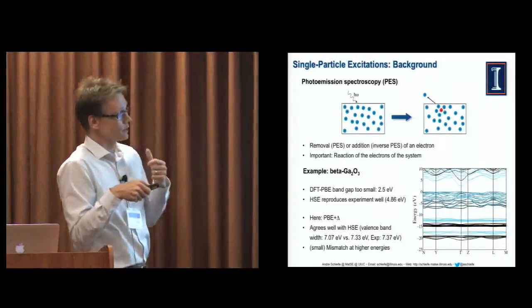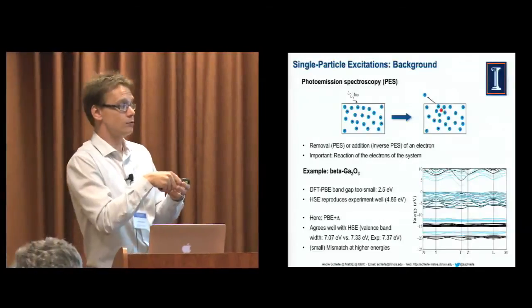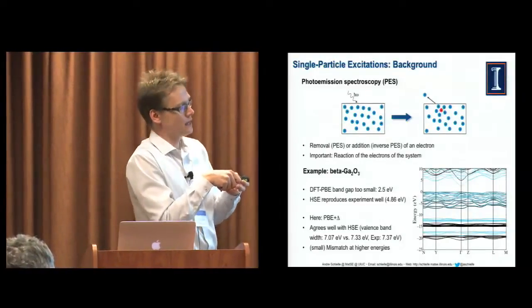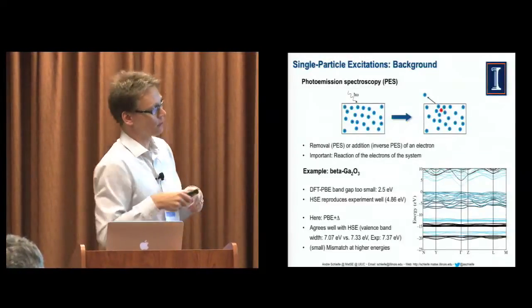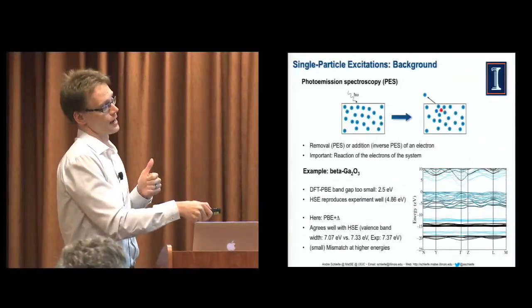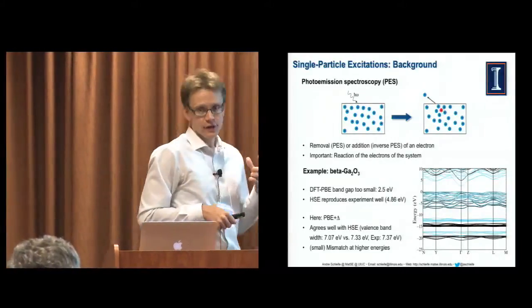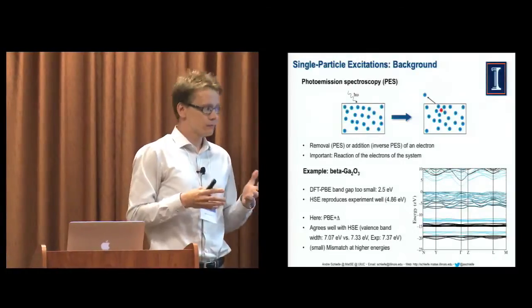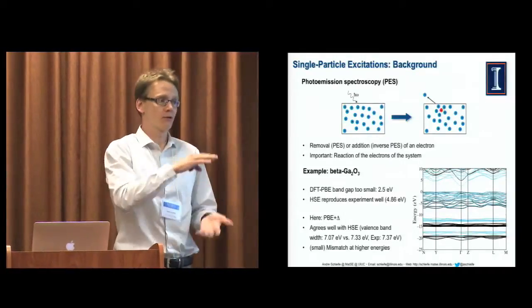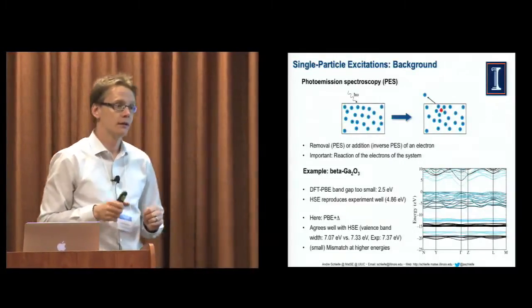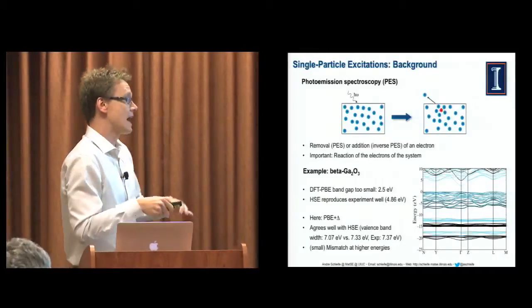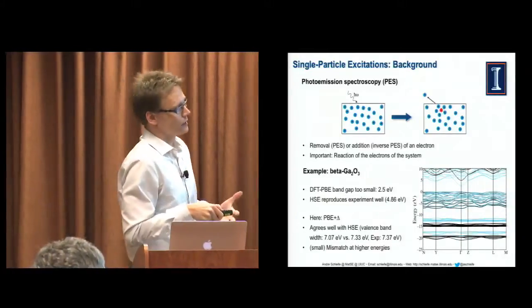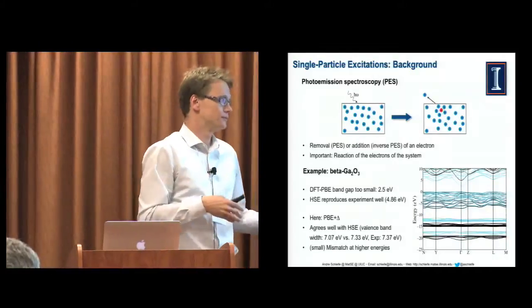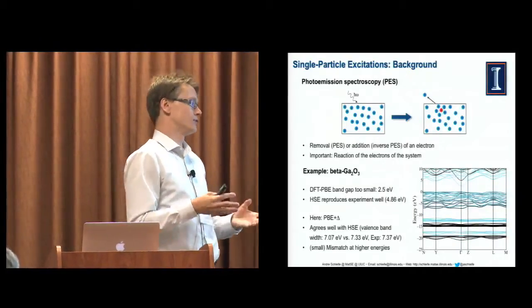If you compare that to experiment, you'll see that this band gap is way too small, right? So in this particular case, we obtained, I guess, 2.5 electron volt. The experimental one is closer to 4.9. That is a tremendous difference, because if you think of optical absorption, this is exactly the spectral range that you want to describe accurately, right? And in this case, we use the hybrid functional to compute a band structure that is closer to experiment.